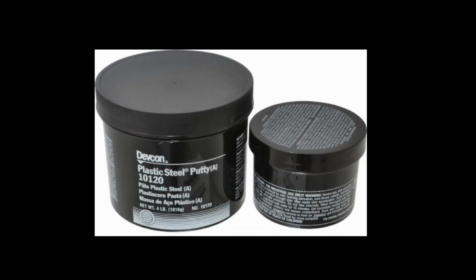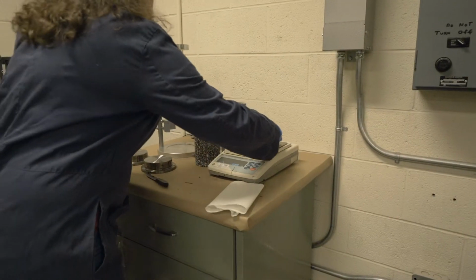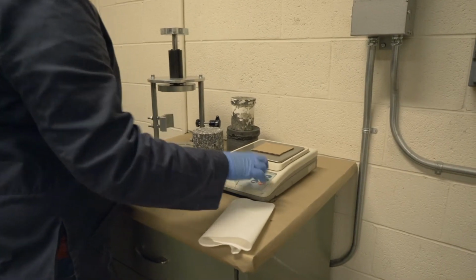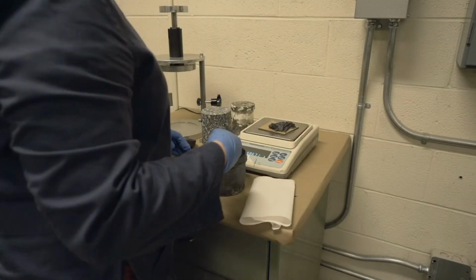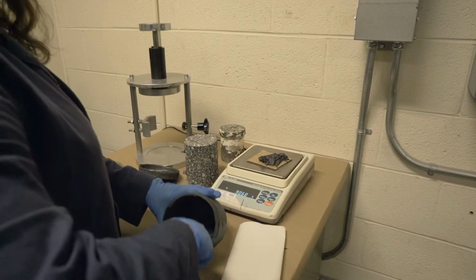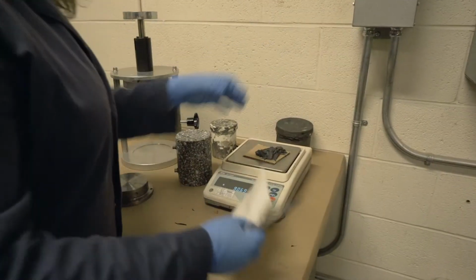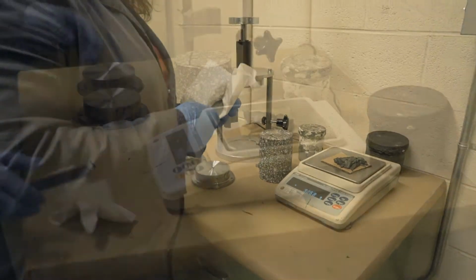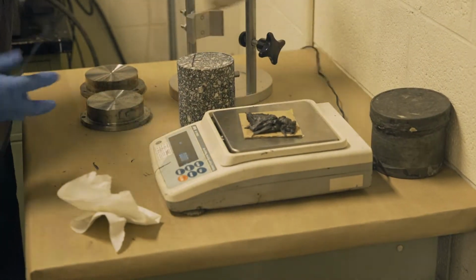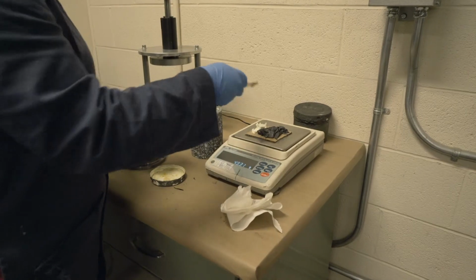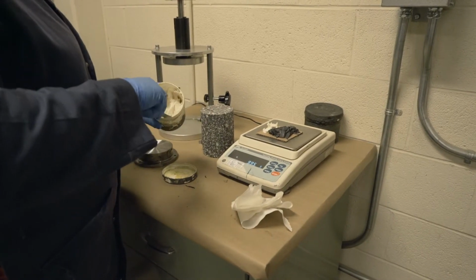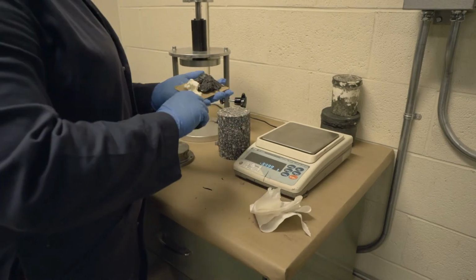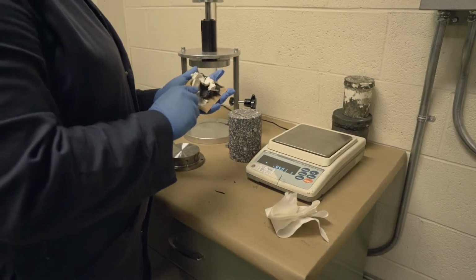The epoxy used in this video is DevCon 10120. If you are using a different epoxy, follow the manufacturer's mixing and curing instructions. Place the mixing surface on the balance. Tare the balance. Measure out approximately 90 grams of the black epoxy resin on one side of the mixing surface. Then wipe the spatula on a clean paper towel or rag. Tare the balance and measure out approximately 10 grams of white epoxy hardener on the other side of the mixing surface. Mix the two parts of the epoxy together with the mixing tool until a uniform streak-free gray color is achieved.